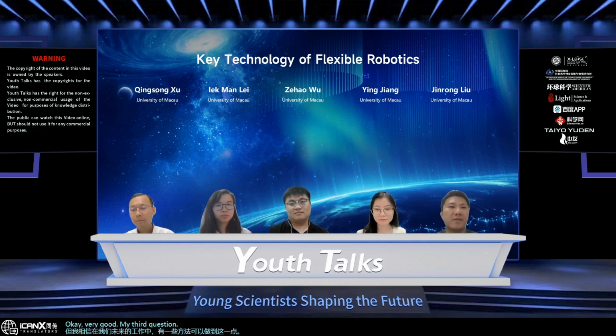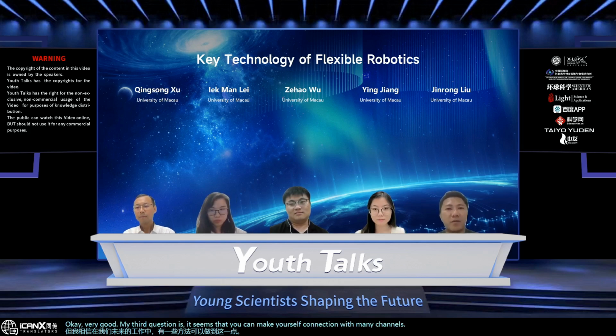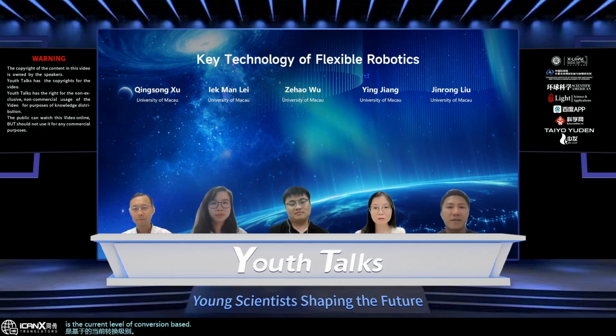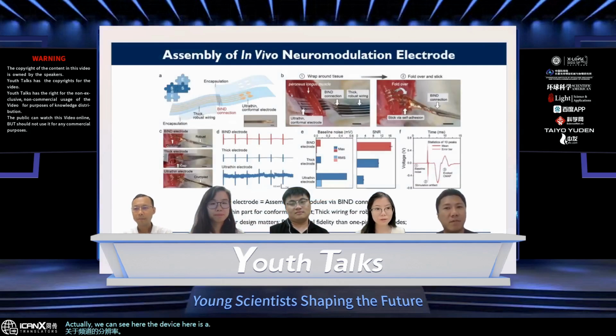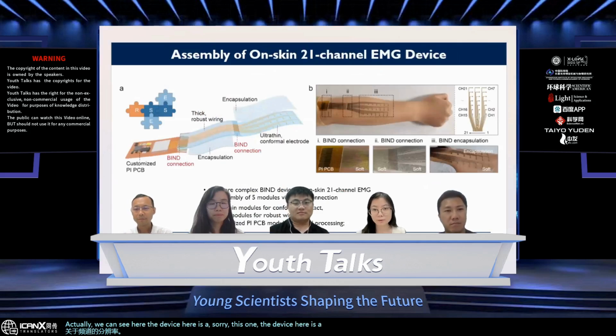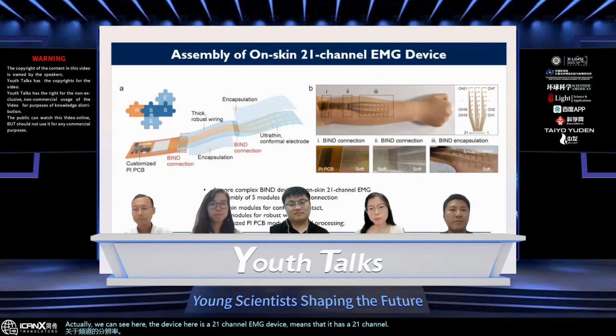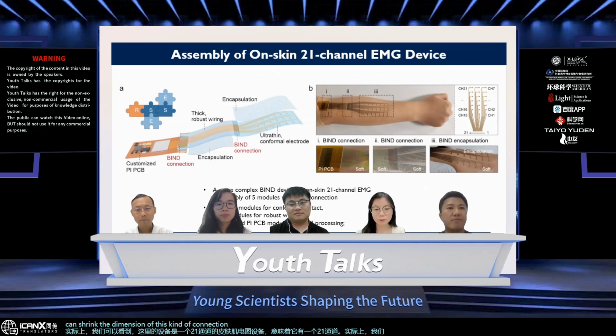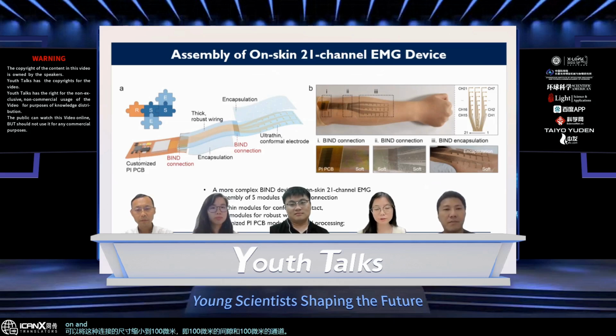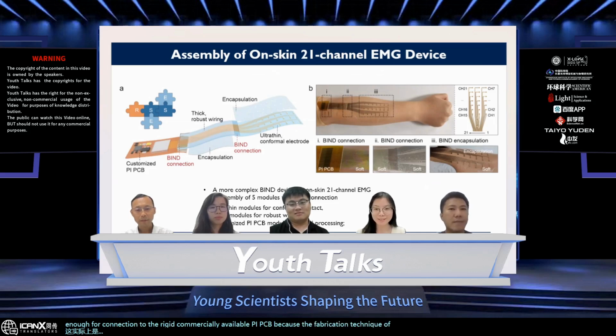Okay, very good. My third question is, it seems that you can make your soft connection with many channels. So what is the spatial resolution of your connections, and what is the current level of commercial paste? Oh, on the resolution of the channel, the device here is an on-skin 21 channel EMG device, and actually we can shrink the dimension of this kind of connection down to 100 micrometer, that is 100 micrometer gap and 100 micrometer channel. And this is enough for connection to the rigid commercially available PI PCB, because the fabrication technique of PI PCB